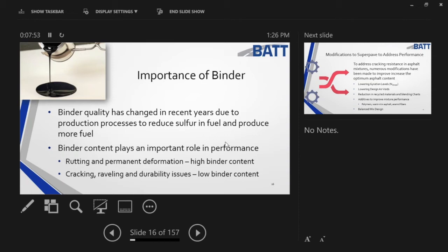Well, the binder is still going to meet the minimum quality that SuperPave has spelled out, but there may be things there that we just can't measure in rheometry, or in what they call a DSR, a dynamic shear rheometer, or in a bending beam rheometer. Binder content plays a big role in the performance. And again, that rheometry helps us to understand the rutting and the cracking components.